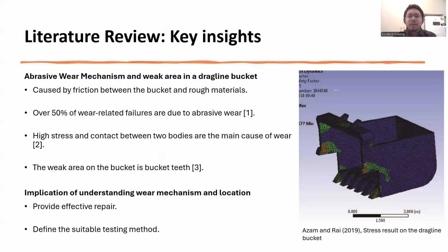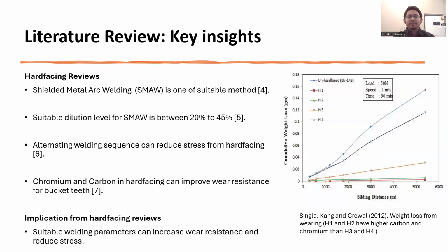Next, let's talk about abrasive wear. Abrasive wear is the primary cause of dragline bucket failure that can occur when the bucket moves against rough surfaces like rocks and creates high stress on the tool. Many studies have shown that over 50% of wear is abrasive wear. Moreover, research indicates that the bucket teeth are a weak area on the tool. This is shown in the right picture here. So understanding this wear mechanism helps in developing effective repair methods and testing criteria.